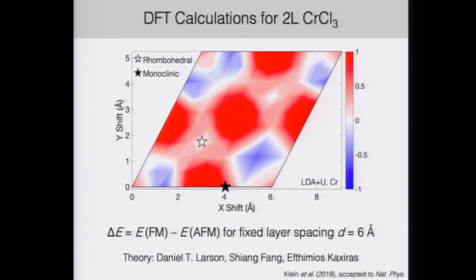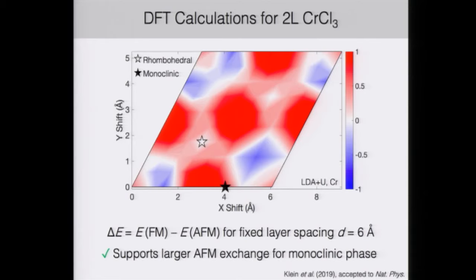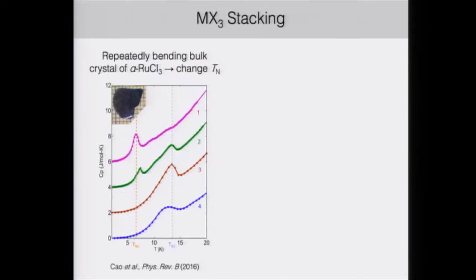They further performed calculations where at fixed layer spacing, they sheared one layer with respect to one another. And they again found that the monoclinic phase, shown here in the black star, has a larger antiferromagnetic exchange than the rhombohedral shown in the white star. And so this supports our larger antiferromagnetic exchange for the monoclinic phase, which we believe ultrathin chrome chloride to remain in down to low temperatures.